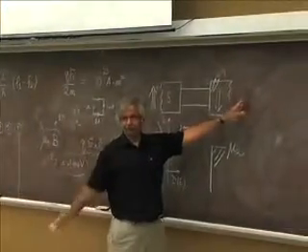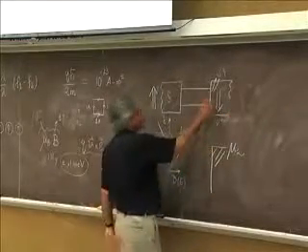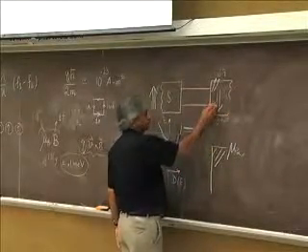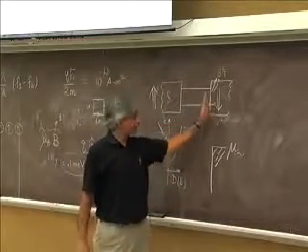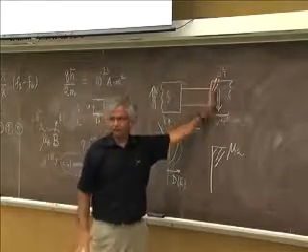But of course that is true. You couldn't do anything to this magnet if it was a micron or even 1/10 of a micron thick. The ones that are getting turned are like a few monolayers. These are nanomagnets in thickness. As far as area is concerned, they're fairly big. It's the thickness that is small.